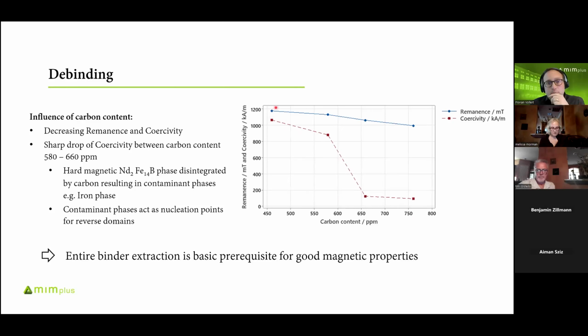What you basically see is that both magnetic properties decrease with increasing carbon content, but between 580 and 660 ppm, the coercivity does a very sharp drop. Our guess is that at that point, the hard magnetic Nd2Fe14B phase is disintegrated by the carbon, resulting in a shift to other areas of the phase diagram, which could lead, for example, to iron phases that are not wanted in the magnet. These contaminant phases then act as nucleation points for reverse domains. So it's really crucial to remove the entire binder from our magnets in order to get good magnetic properties.